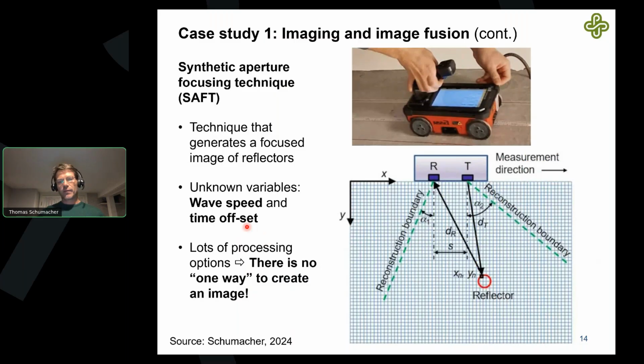There are two unknowns that we have to determine. One is wave speed. As I said, we calculate distance divided by wave speed, so the wave speed needs to be determined. That's a function of the material. And there's a time offset that we also have to guess so that the reflectors eventually line up in the correct position. So there's some calibration required.